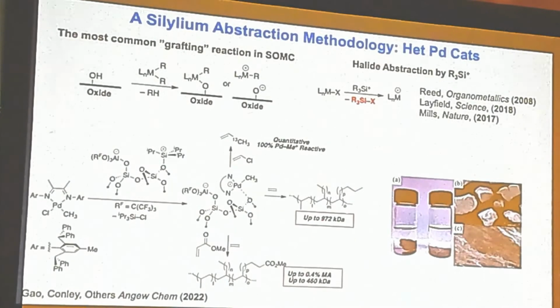We generate very high molecular weight polymeric products. This is if you take this catalyst activated with a halide abstraction reagent in solution, you generate this sort of globular massive polymer. If you take the heterogeneous material, you generate these really nice pellets, and you can see that from the SEM images that we're generating pellets with the heterogeneous and just a mass for the homogeneous catalyst. And to my knowledge, this catalyst produces the highest molecular weight copolymer when we do a copolymerization of methyl acrylate and ethylene.